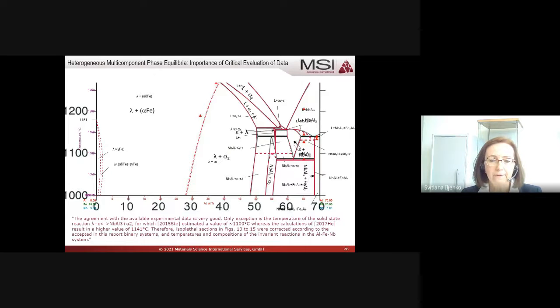Here we have niobium aluminium. Now this is a ternary system, niobium aluminium iron, and here the red lines, this is a calculated diagram. No, the red line is a critically evaluated diagram and the black one is calculated. The point here was that our authors had these two different works. One is experimental, one is calculated.